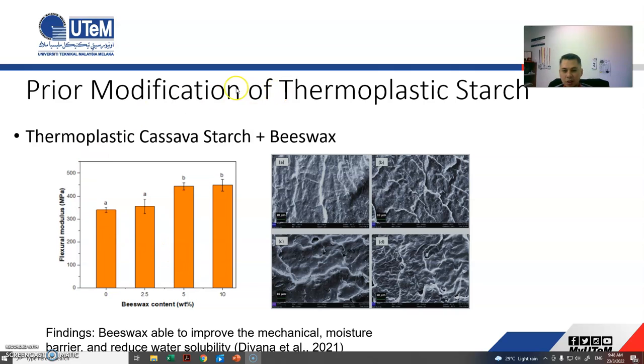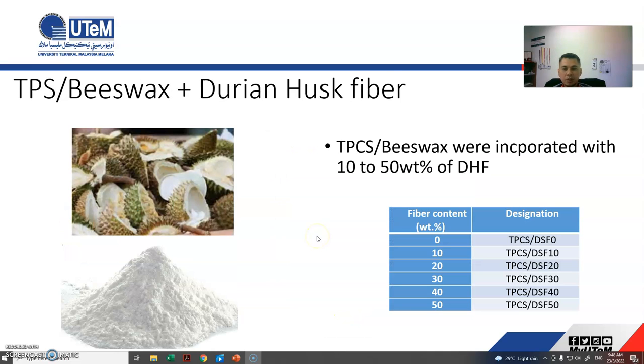So instead of using thermoplastic starch alone as the base material, in a prior study we conducted an investigation using beeswax to improve the properties of the thermoplastic starch. Here we can say that the beeswax is able to improve the mechanical properties, the stiffness, and also reduce the moisture, increase the moisture barrier, and reduce the water solubility. And there is no major impact to the structure of the materials following the addition of beeswax.